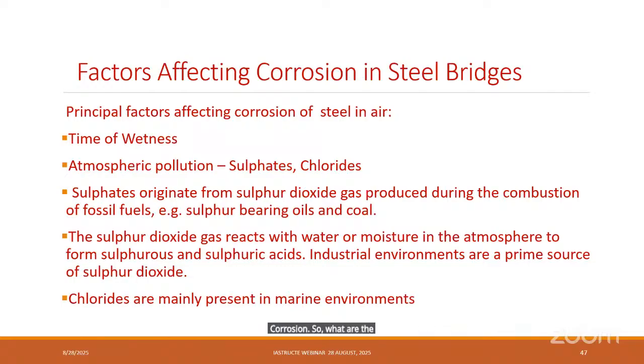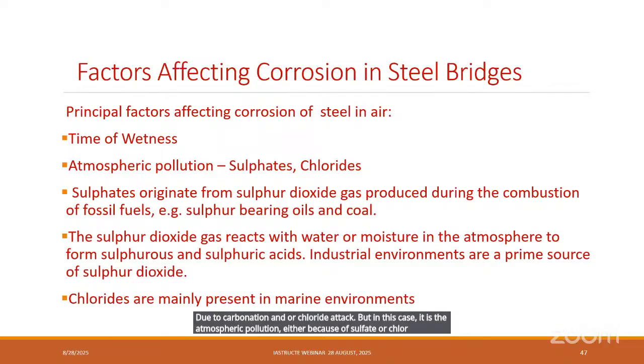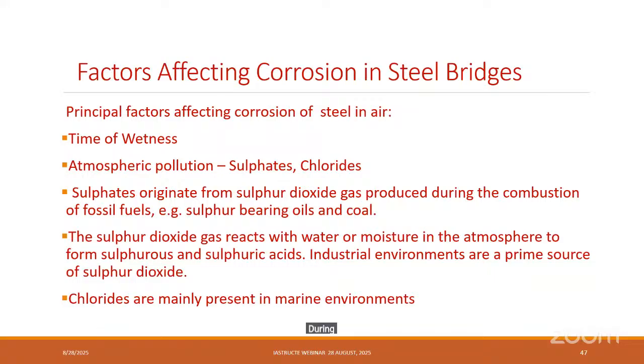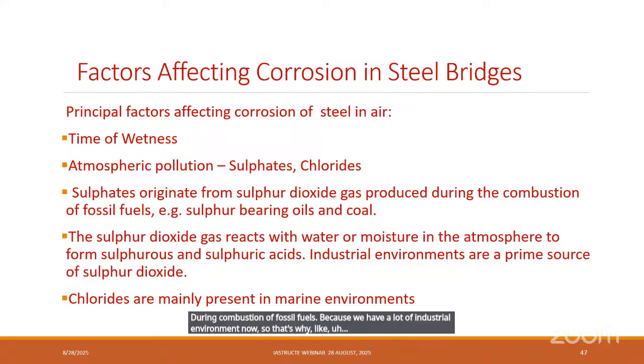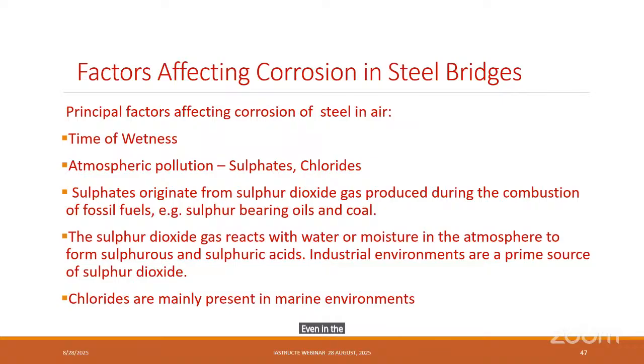So what are the factors which affect corrosion in steel bridges? Basically, the time of wetness, that is how long the surface is wet, and alternate wetness and dryness, and the atmospheric pollution. Like for example, when you have concrete with steel embedded in it, the corrosion may be either due to carbonation and or chloride attack. But in this case, it is the atmospheric pollution, either because of sulfate or chloride, that the surface is getting corroded. So sulfates originate from sulfur dioxide gas produced during combustion of fossil fuels, because we have a lot of industrial environment now. So not only in the marine environment where chloride is mainly present, even in the industrial area, because of the sulfate, the corrosion of these steel bridges is happening.